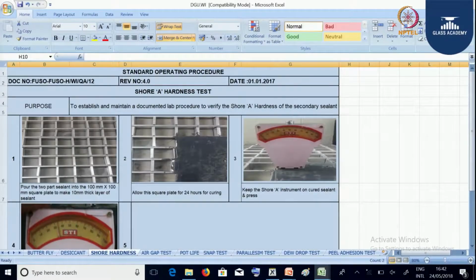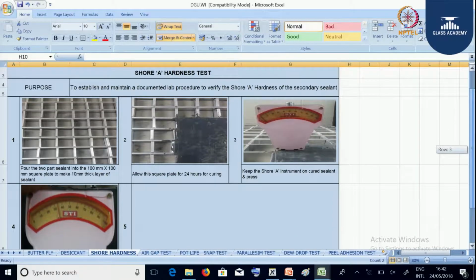Next we see the shore hardness test, used to check the hardness of the secondary sealant. The procedure is: we take a 2-part sealant into a 100 by 100 mm square plate of 10 mm thick layer, then apply secondary sealant on that 100 by 100 mm area, and after 24 hours of curing we try to see the hardness with a shore hardness tester.